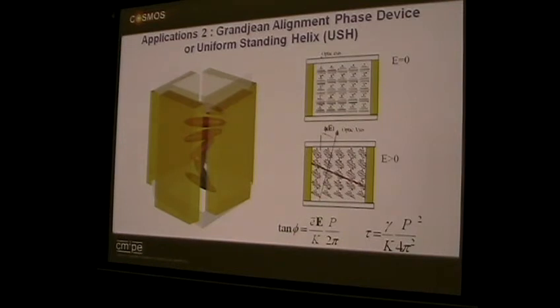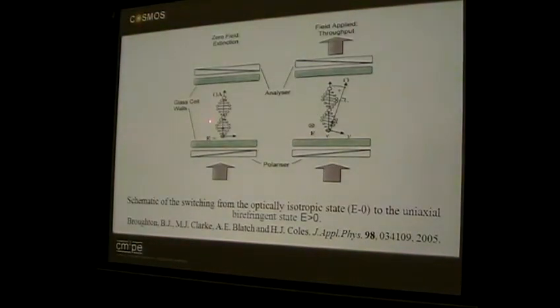But if you only have one pair of electrodes, just take one pair away, then I can apply a field across the system, an in-plane field, so that's just the same as many LG displays, I guess Hitachi's early displays. So you apply a field in the plane of the device and the helix axis tilts. Reverse the polarity and it tilts the other way. So, how does that give you a device? If you look down on the device, so this is the effect again, that was the effect that I'm talking about. There's your helix, and then a field coming out towards you, as I've drawn it in this geometry, and the axis tilts. The tilt is always orthogonal to the field, at right angles to the field. Okay? So then you get the tilt. Reverse the polarity, and it tilts the other way.